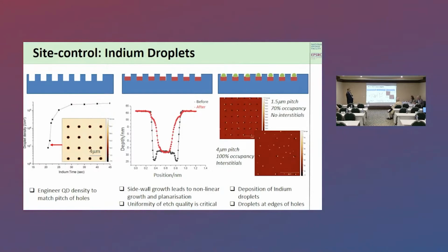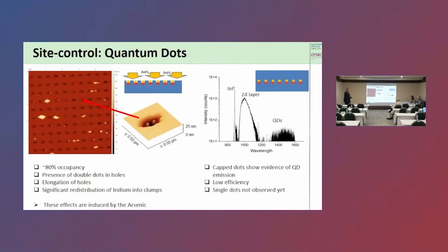If we supply arsenic and convert them to quantum dots, what happens? Do they disappear or do they not disappear? And the answer is they don't disappear, but some interesting things happen. So what happens when we apply the arsenic and convert to quantum dots is that actually we do get quantum dots and we do get the site control. So actually we have about 80% occupancy of dots. But interestingly, we form 2 dots in the holes.